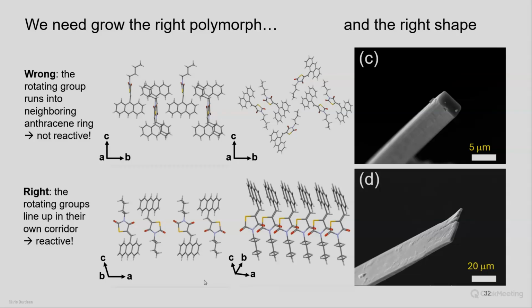So your first problem is, unfortunately, these polymorphs are the same energy according to the calculations. So the way you grow them is you just grow them under very different conditions, both reprecipitation, but different solvents or different surfactants. But you have to get the right polymorph for the cis-trans, and it has to be a head-to-head packing where the anthracenes are all on the same side. And it's not clear that that's energetically favored by a huge amount. Now, the polymorph has to have room for the cis-trans isomerization to happen without undergoing some steric interference.